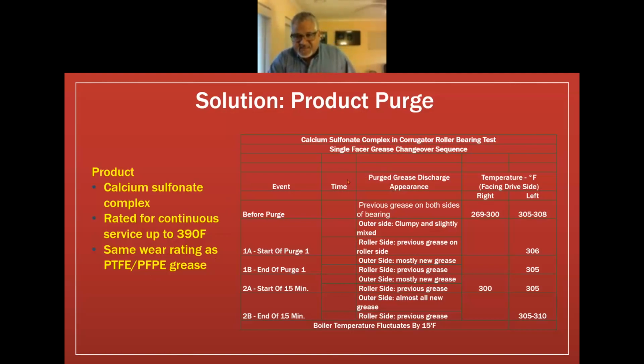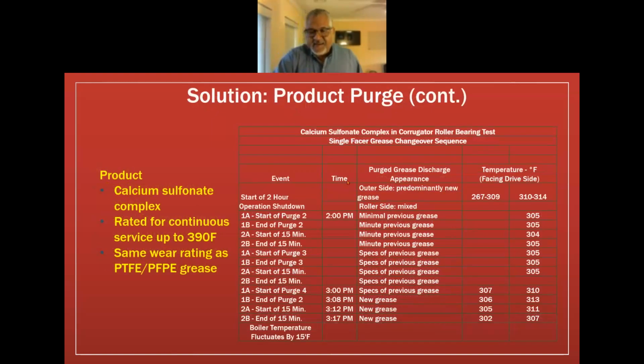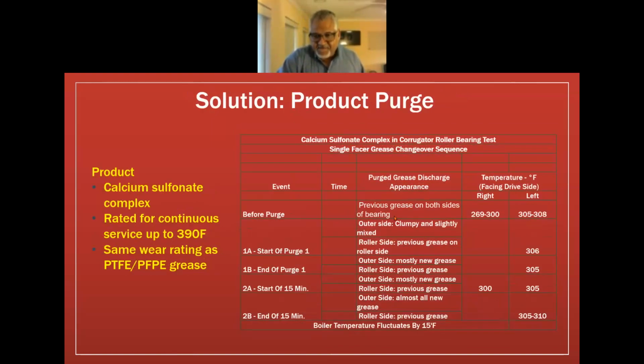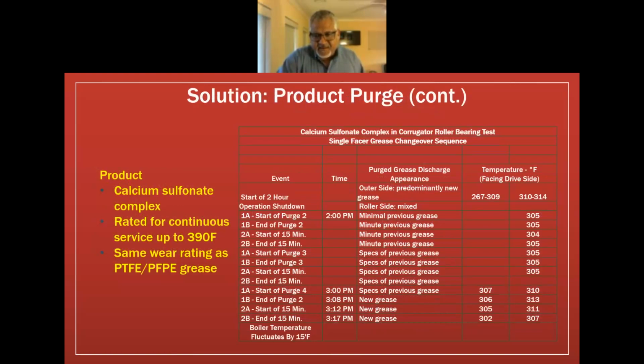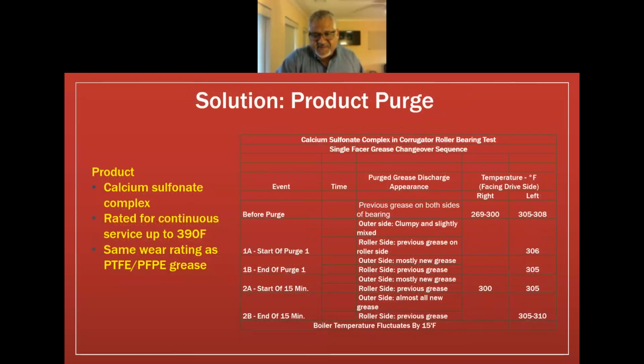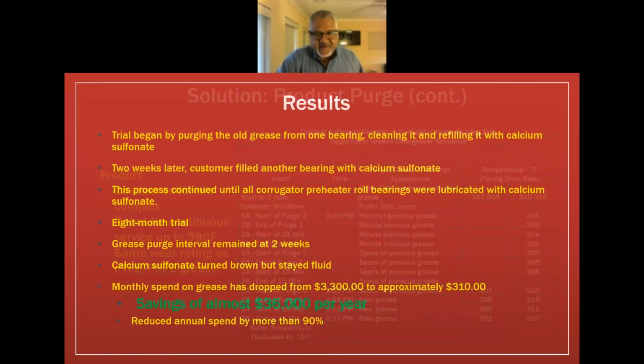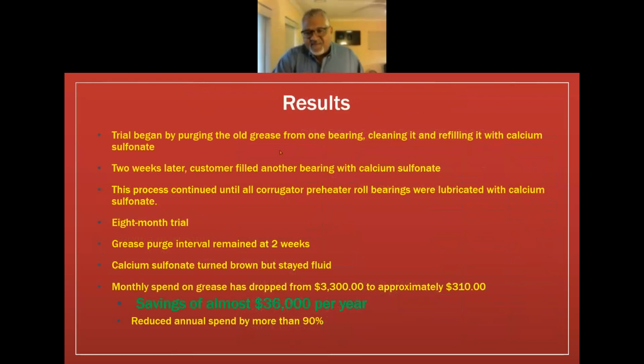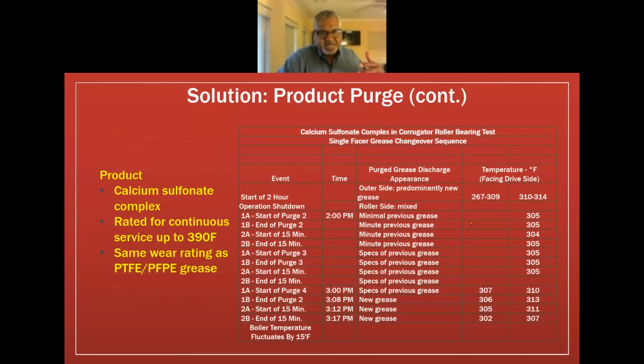So I just really showed this slide and this slide to demonstrate that I actually sat there for a day or two and logged the condition of the grease as we purge. So the process was to purge, let it run for 15 minutes, and monitor the appearance of the grease.